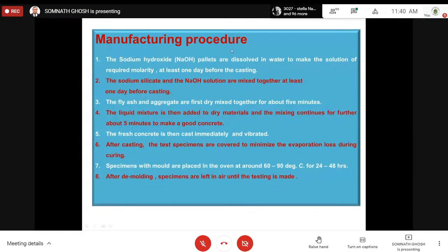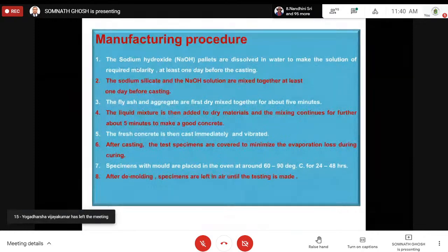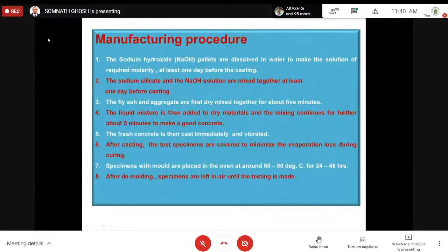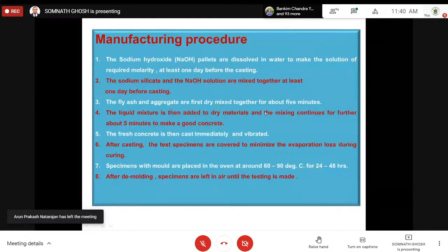Now you see the manufacturing procedure, this is very important. Those who are doing research in this area should be extremely careful about it. Sodium hydroxide pellets are dissolved in water to make the solution of required molarity at least 1 day before the casting, not on the same day. You won't get a good result if you do it on the same day. Sodium silicate and sodium hydroxide are mixed together at least 1 day before casting. Of course, we are not doing it now because of different other problems. In the winter it is different, in summer it is different. You can do it 3-4 hours before casting. Then fly ash and aggregates you have to dry and mix together, dry mixing. And then you have to add all these things slowly.